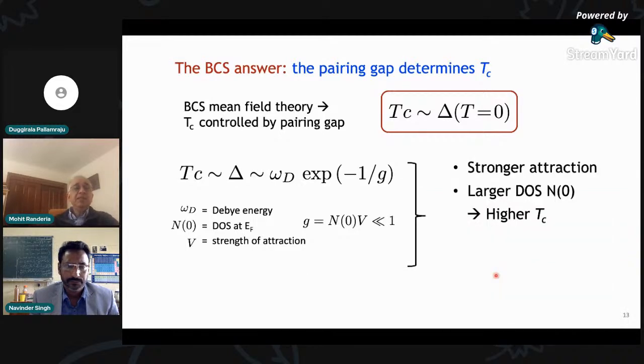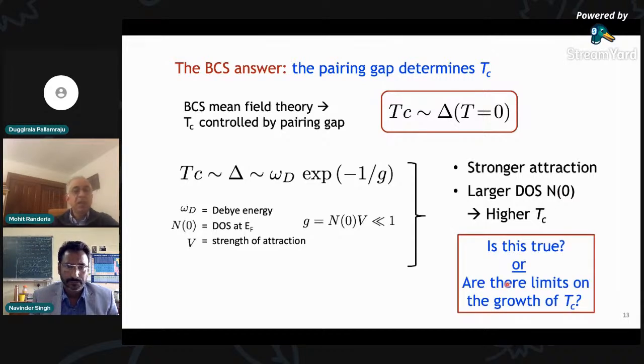So the point is that if you look at a formula like this, then the experimentalist feels wonderful. If I can somehow make a stronger attraction, or if I can have a larger density of states, then basically I'll enhance g. And if I enhance g, I'll get a higher TC. So it seems that by choosing a suitable material having more attraction, larger density of states, there's no limit to TC. Okay, is this true? Or is this actually a misleading statement? And there, in fact, are limits to the growth of TC.